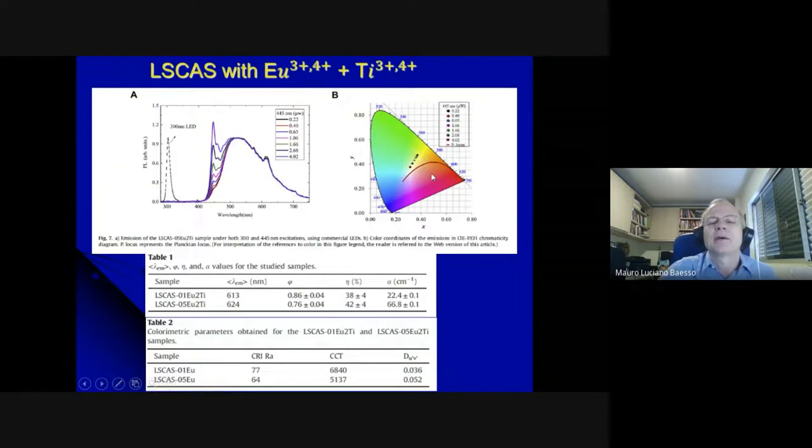And then we calculate the Planck curve, the chromaticity diagram, and then change the power of the LED. You see, we can go very close to the white light position, which, as I said, is 0.33 and 0.33 for X and Y. It's this position in the Planckian curve. In the back, in the table, the first line, Table 1,